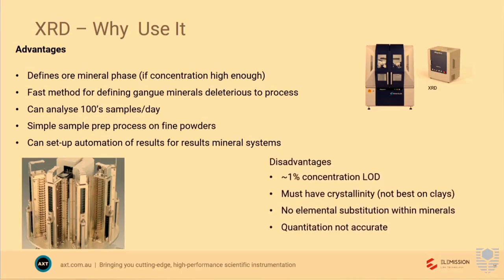One of the limitations or disadvantages of the technique is that the detection limit's about 1%. You must have crystallinity, so the minerals must be crystalline, not too finely pulverised. It's not the best on clays, because clays tend to be a little bit finer than 5 microns. It's very difficult to determine the elemental substitution within minerals. A high-end researcher can work out by a little bit of a wavelength shift if you've got a solid solution series. But generally in industry you can't, and the quantification is not accurate. Even though the Rietveld analysis deconvolutes those spectra to determine how much of each mineral is there, it's not particularly accurate.